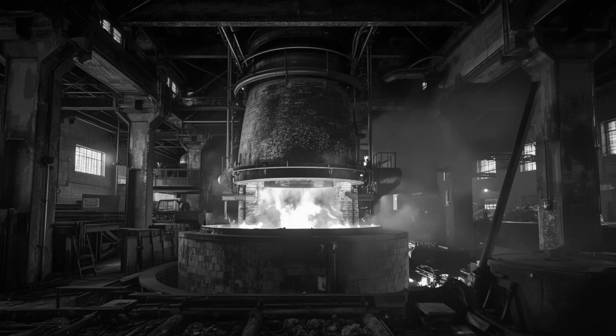He brings this to the attention of Samuel Brennan, the materials engineer who sourced the original refractory brick. Brennan examines samples from different heights using a micrometer and a simple crushing test. The bricks from the lower courses are measurably smaller in dimension than when they were installed, and they're harder, more resistant to mechanical pressure. The bricks from higher up show less change. The pattern correlates exactly with temperature. The hottest zones show the most dimensional change. Brennan orders a chemical analysis.